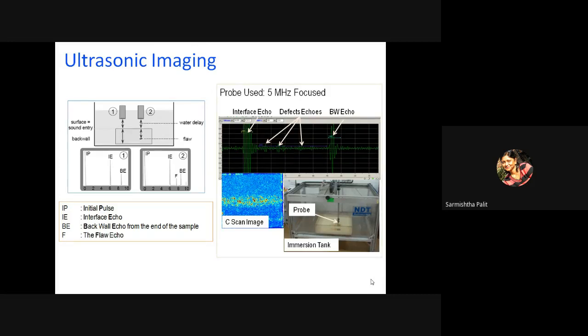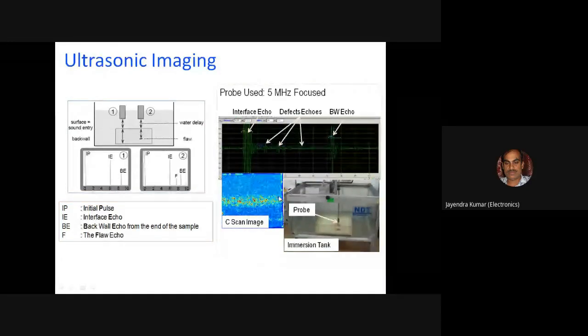If I get all this information by placing my gate, which picks up all those amplitude values, and then I plot the intensity plot, you can see one image showing here. There are lots of red dots, which are very clearly high-amplitude defect echoes. So by looking at this picture, you can say all these red dots are defects, so my material has many defects. If I go to a defect position, it will also tell me at what depth it is. So you get your depth and your X and Y location, and then you can take a proper call on what to do with this material.